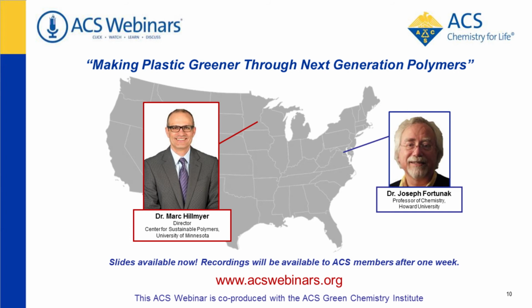I'm combining a couple of questions here together, asking for a bit of discussion about how you can design to speed up or slow down the biodegradation of PLA. We just published a paper, and many people have looked in this area, about copolymerizations with lactide that lead to weak linkages in the backbone, linkages that are more hydrolytically sensitive than the aliphatic polyester that's in PLA. Because PLA typically gets assimilated in a compost environment by first hydrolysis of the macromolecule down to smaller molecules that ultimately can be processed by the microorganisms in a compost.